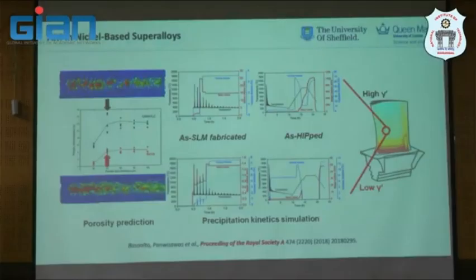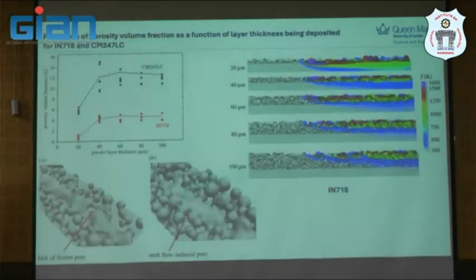why I do what I do. When we have a defect, we predict porosity. This is an old slide, just to introduce something, and then you have different predicted secondary phase formation, and also during post-treatment in hipping, you can get different distribution of the size of the particle, which is important for the material life prediction later. So this is the thing.